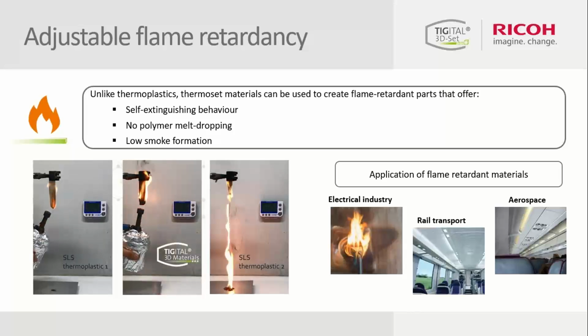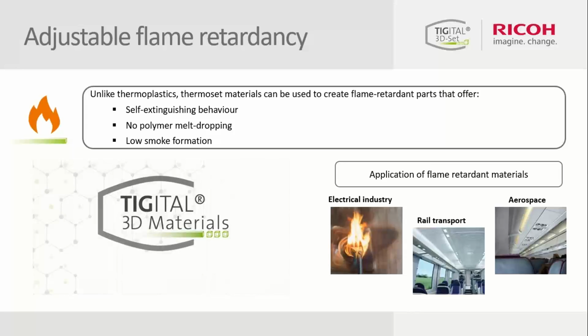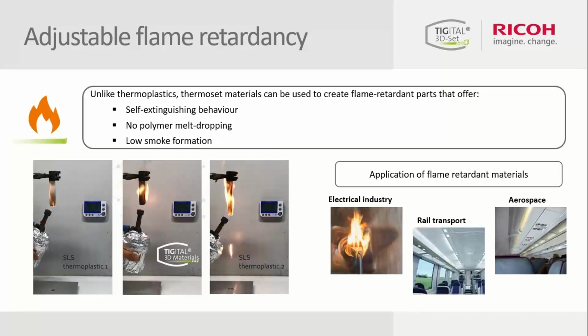And sometimes I really think that seeing is believing. So as you can see on the video on this slide, which compares a Thermoset flame retardant material in the middle with two thermoplastic materials on the side. The Thermoset, when exposed to fire or to a source of heat, shows this self-extinguishing behavior. You can see there is no polymer melt dropping, and they also generate very low smoke. So we have tested the material according to the UL 94 testing, and it is possible to achieve V0 flammability rating for a minimum thickness of 1.2 millimeter.